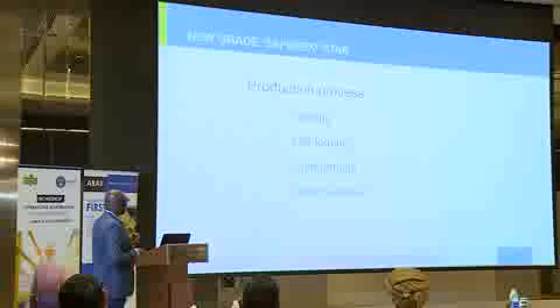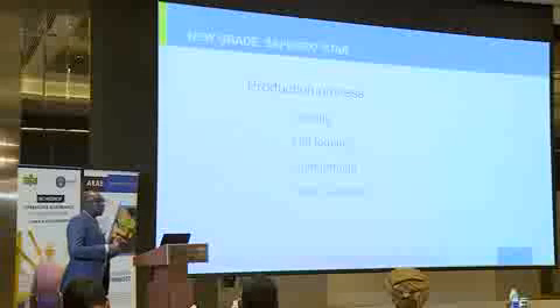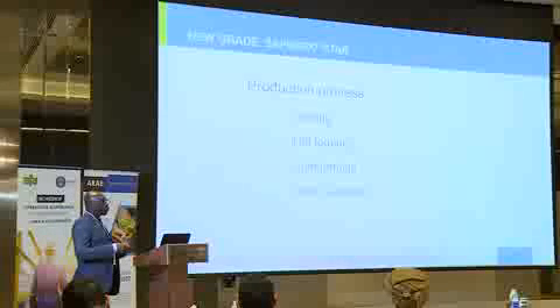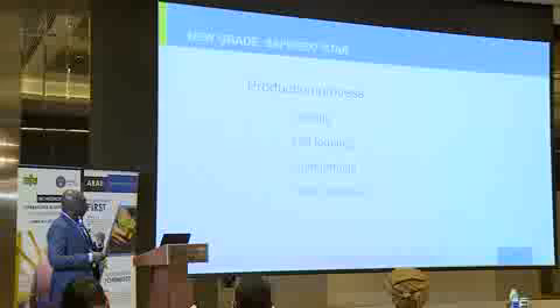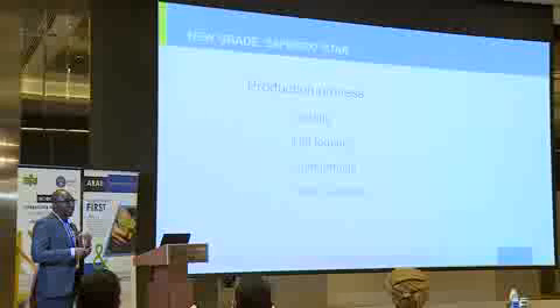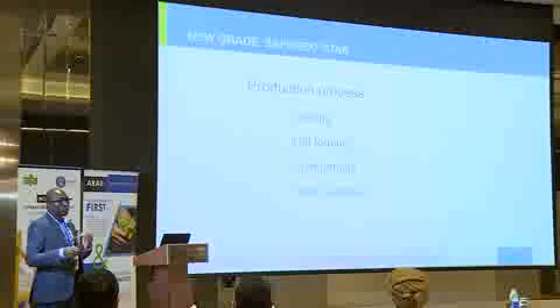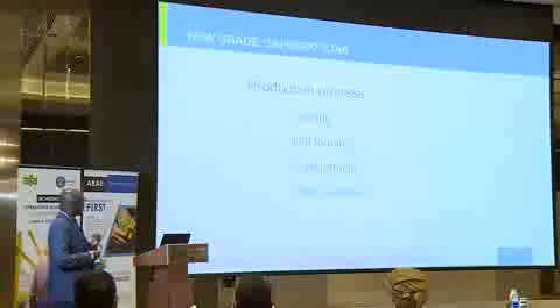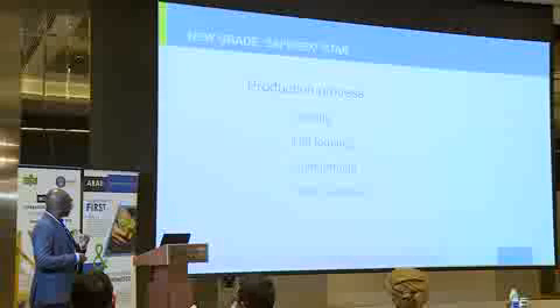There was another thing that we did think about. In materials, properties are related to microstructure. But then the microstructure is also influenced by your production sequence. So we made sure that for the testing coupons that we made, it goes through the same processes that an actual stripper tube will go through before it gets to the client. So we had the same casting, hot forming, cold forming, and heat treatment processes.